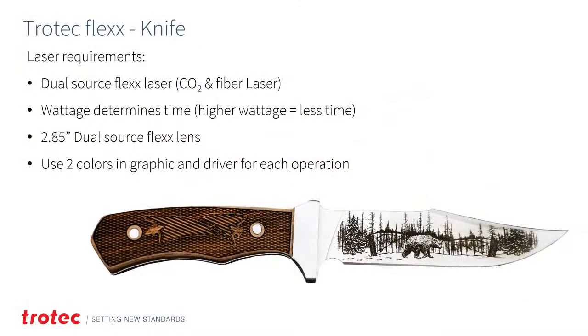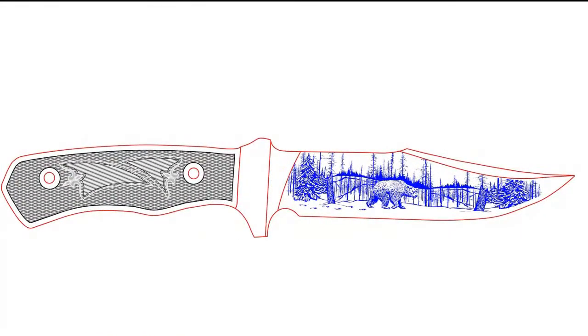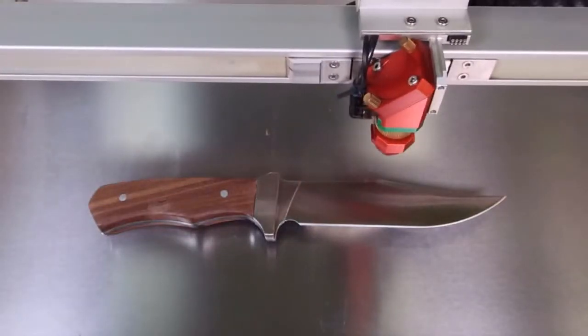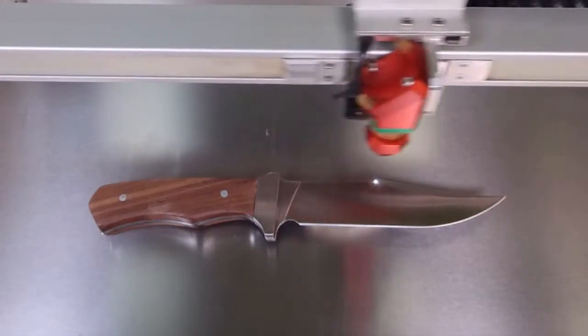And then the last one is taking it a step further. Not only are we engraving with the CO2 onto the wooden handle, but we're also going to use the checkering three-dimensional relief mode grip pattern into the handle, combined with the fiber laser with a scrimshaw-type imagery into the blade itself. So here's a case where I've taken a hunting knife using the dual-source CO2 Flex 2.85 CO2 fiber laser lens using two different colors, and then we'll etch that graphic. And so same gradient graphic using relief mode in kind of black gray. In this case, the fiber laser will engrave onto the blade.